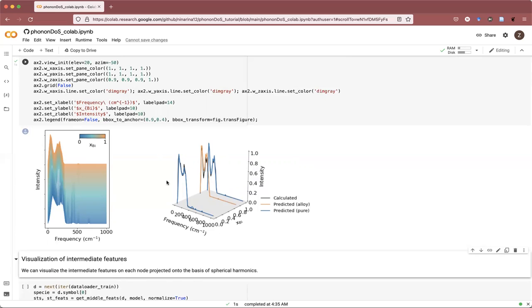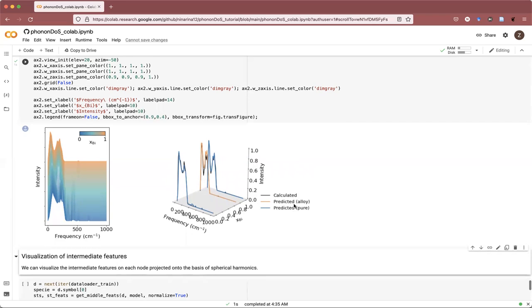And in this figure, in the right panel, what we are looking at is the comparison between the predicted and the calculated density of states for the parent materials, as well as the alloy system calculated from the virtual crystal approximation. And we can see pretty good agreement between our predictions and the ab initio calculations.